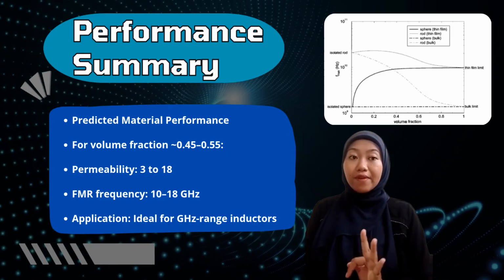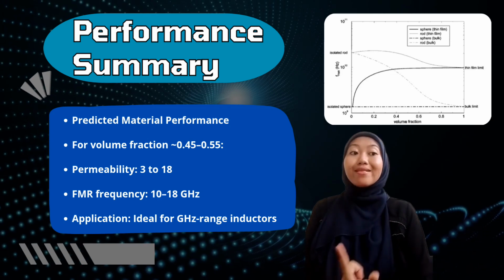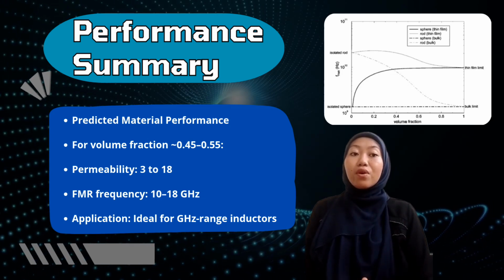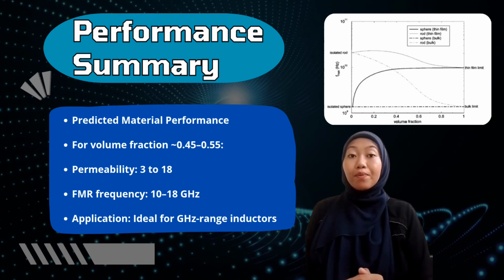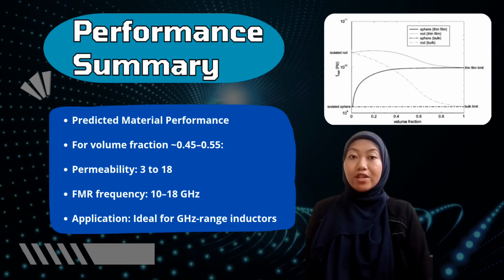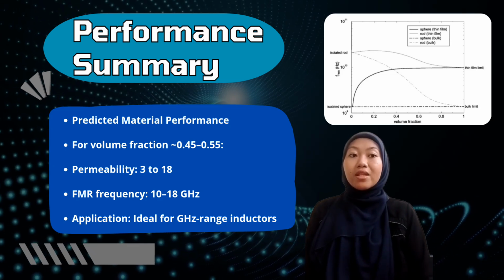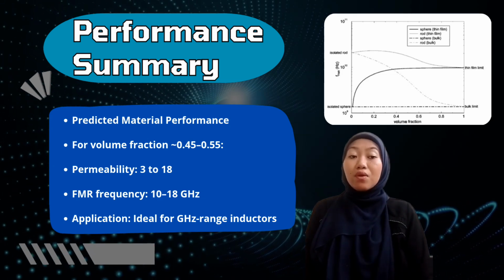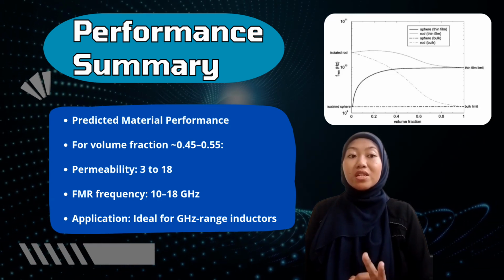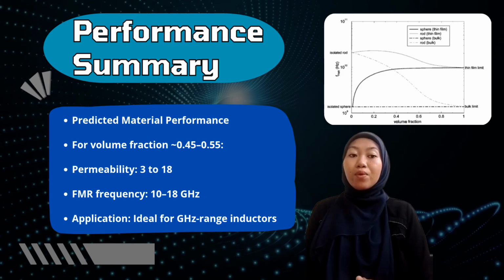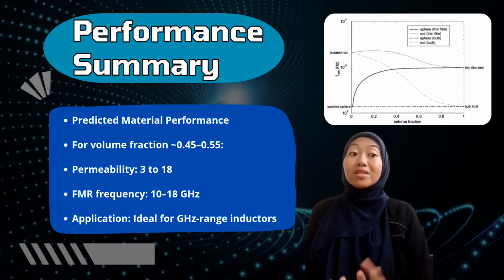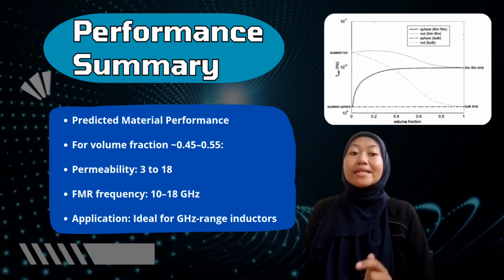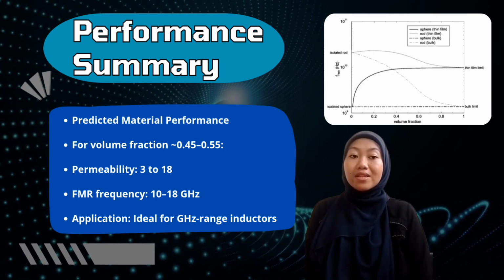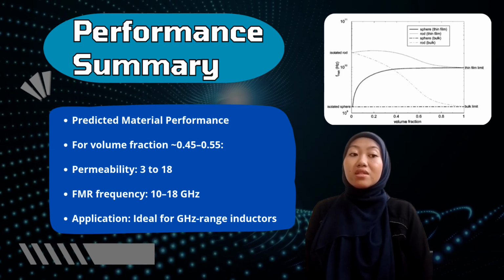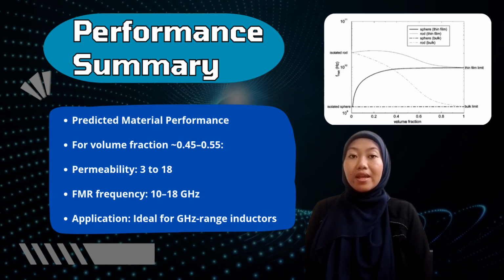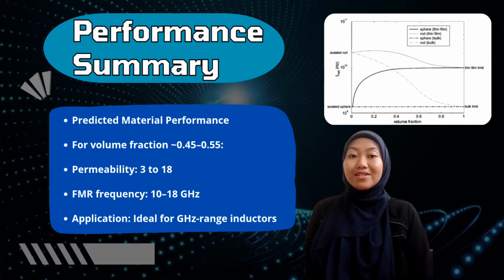By combining all three factors, small particle size, optimal shape, and thin film-like packing, we reach a range of configurations with outstanding magnetic properties. For a volume fraction of 45 to 55%, the modeled composite showed low-frequency permeability values between 3 and 18 and ferromagnetic resonance frequency between 10 and 18 GHz. These values are highly desirable in applications such as integrated circuits, where compact and efficient magnetic components are essential.